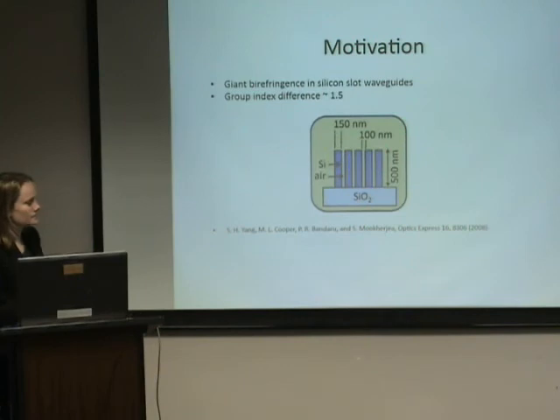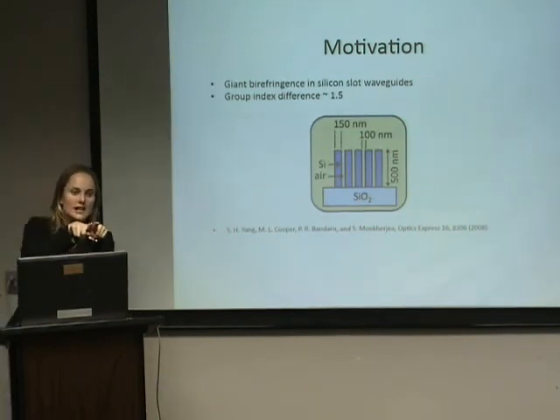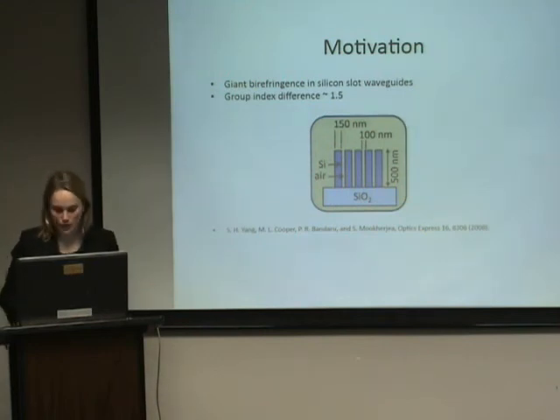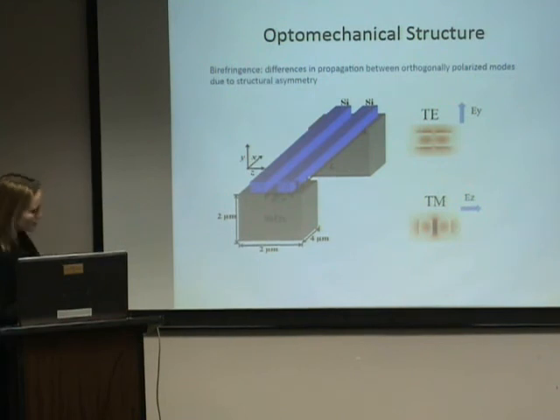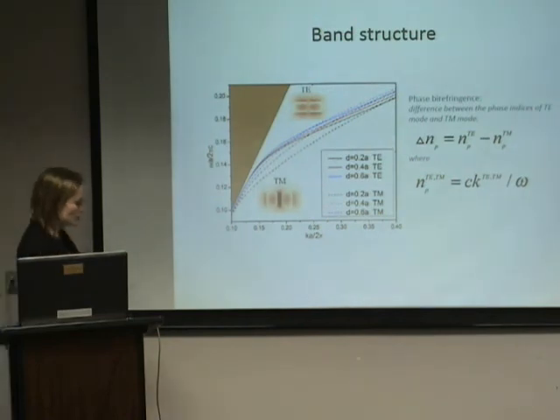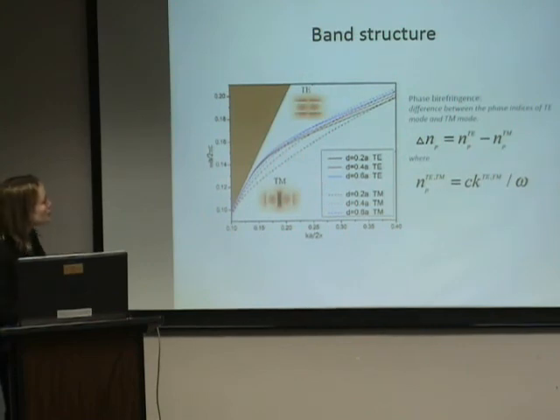We have something that looks like a waveguide with a slot in it. And so now we have a force that moves it, so we should be able to change the birefringence, and by quite a bit. So that's shown here. If we consider a two-beam structure that's suspended, the mode that's polarized this way and this way have quite different properties. They propagate at different speeds. And we can calculate dispersion relationships, so we can calculate exactly what the characteristics of those modes are to figure out frequency versus wave vector and figure out the speeds and the phase index, which is characteristic of it.